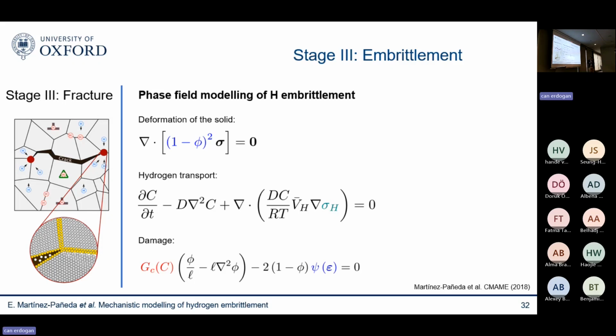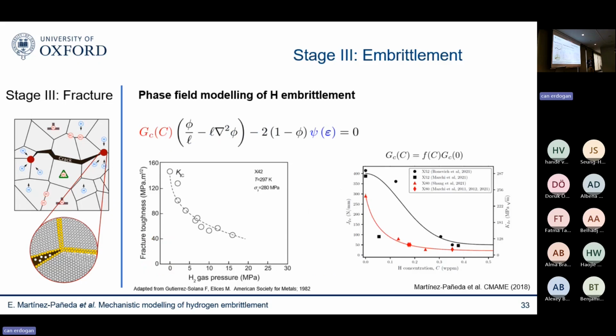And there are many ways you can do that. Of course, we know from experiments that this is the case. I showed you some data before. This is pipeline steels. You can see how, as you increase your hydrogen pressure or your hydrogen content, your fracture toughness goes down. So there is plenty of experimental evidence, and you can use that experimental evidence to fit that toughness value. And this is a lot of what industry or industry collaborators do. They have a lot of toughness versus hydrogen concentration data, so they can just feed the data in and input that as a function.